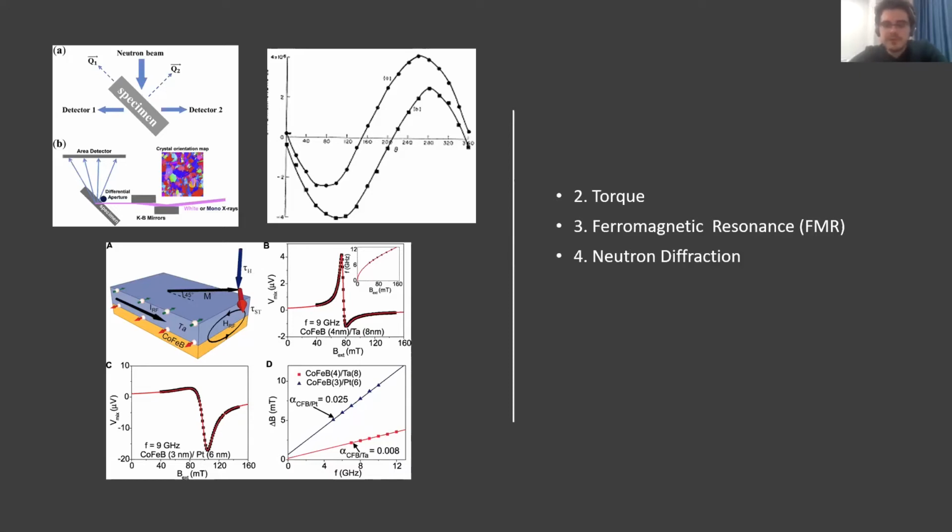But contrary to other effects, neutron diffraction experiments, as far as I can see, give no domain formation or inhomogeneity in the FM or AFM layers. But ferromagnetic resonance, and other techniques we will talk about, gives inhomogeneity in ferromagnetic layers. But these inhomogeneities and domain formations are observed in higher fields than in simple ferromagnetic layers because of the effect of the antiferromagnetic layers on the ferromagnetic layer.